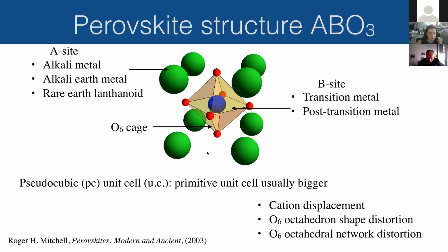But most of the perovskites are not that simple. Their primitive unit cell is bigger, and this is happening because of different types of distortions, which can be summarized like this. Cation displacements, so either the A or the B site, can be moved from the cubic sublattice, let's say. You can also have distortions of the shape of the octahedron, so this could be stretching or compressing of the octahedron, like you get in Jahn-Teller type distortion. And finally, and the one that I think I will go into the most detail on, you can have distortions of the overall octahedral network. So it means that the octahedra do not change their shape, but they change how they are connected to each other. Namely, they rotate and tilt with respect to each other.